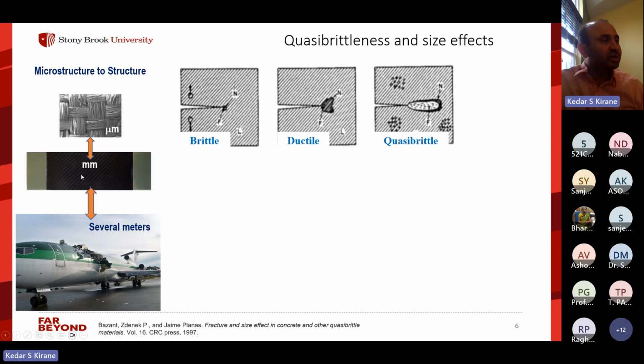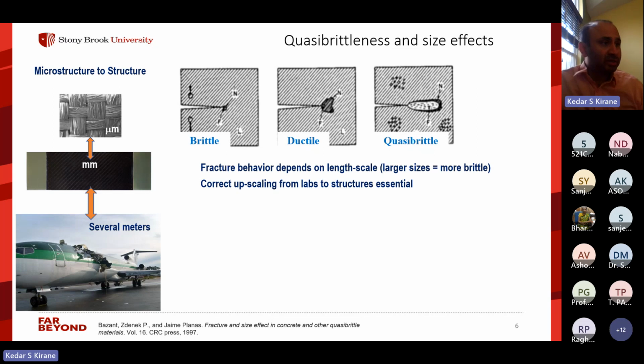And in this intermediate range where we are maybe in the laboratory dimensions, the process zone is of a moderate size, but still not negligible. And so it plays an important role. And so understanding this transitional role played by the process zone is very important in not only modeling it, but also in characterizing the fracture behavior. So essentially the behavior depends on the length scale. Larger sizes are more brittle. And so the scaling from labs to structural size is very tricky.